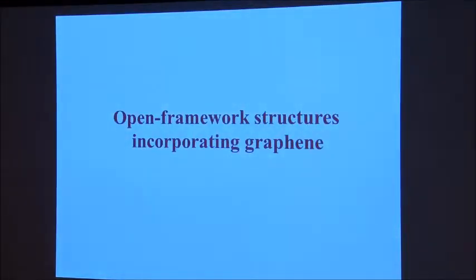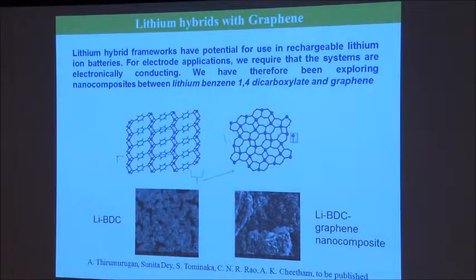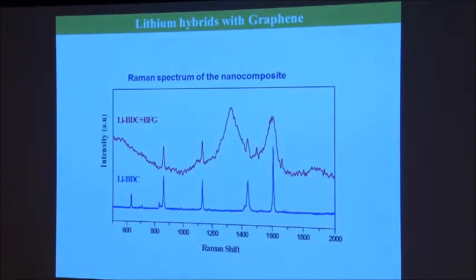And towards the end, the last few frames, what I will show is graphene is so wonderful. Can I make graphene itself as a base for making new kinds of framework structures? Well, this is something we have done. For example, you take graphene, around that you make a metal organic framework of lithium benzene dicarboxylate, for example. And you can see how this is the lithium benzene dicarboxylate, a metal organic framework. I put it in graphene because these are the graphene Raman bands. These bands are also there.